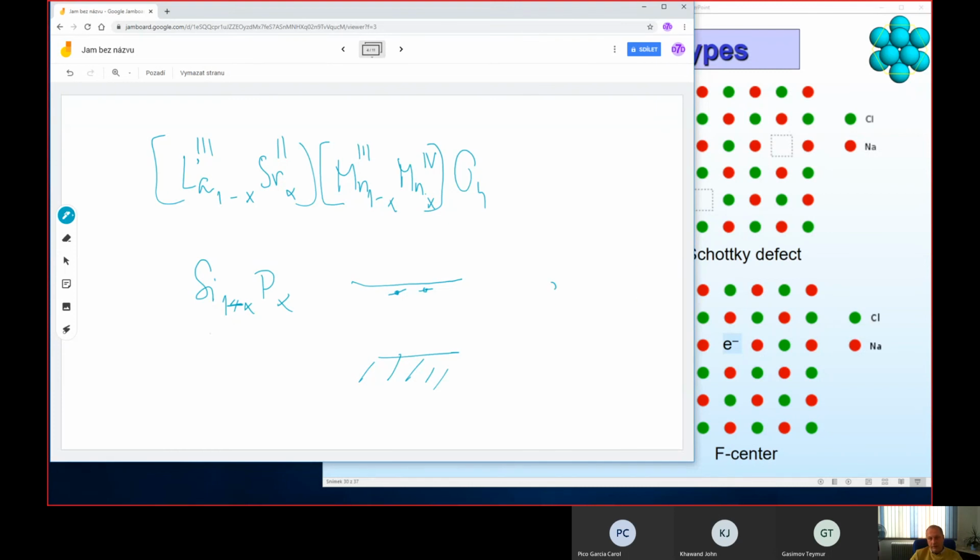So we have the silicon lattice, and here is, for instance, phosphorus, and this electron moves around this substitutional defect and is localized. But once the temperature increases, it can be excited into the conduction band, and it can freely move all over the crystal. So it becomes part of the electronic structure of the parent silicon structure.